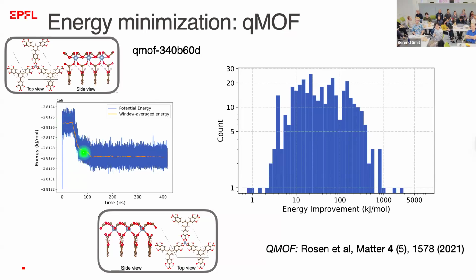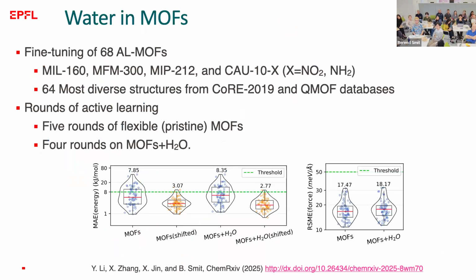So then what we did is we identified the lowest energy configurations on our trajectory, energy minimized, and then compared that energy minimum with the original DFT minimum. And what you see here is all the corrections we needed to apply to get to the true minimum energy. So basically, this method of training a force field very efficiently is very powerful, because if you do an energy minimization, you do many DFT steps, but they're all very correlated. So from a machine learning point of view, you don't learn anything. You're much better off thinking a little bit, how can I use those DFT calculations much more effectively to address these problems? Okay, quickly.